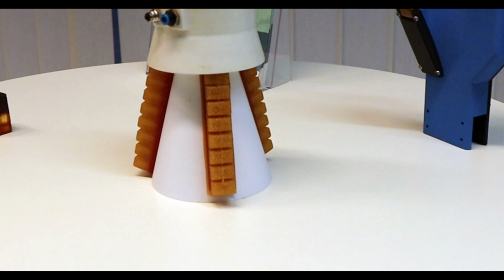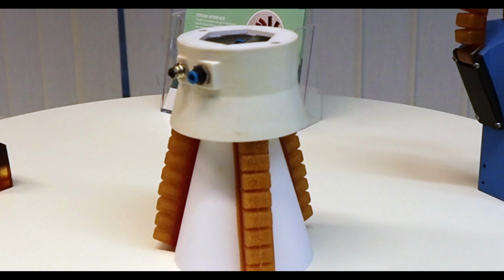Now, besides their self-healing capabilities, which are beneficial for printing soft robots like this gripper, there is another significant benefit. Typically, parts fabricated using this technique have anisotropic mechanical properties, which poses a major challenge. As layers are stacked, the part is weaker along the direction of layering and stronger within the layer plane. However, with self-healing materials, the formation of strong Diels-Alder bonds between the layers solves this issue, as the layers effectively heal or fuse together, which is a very important result.